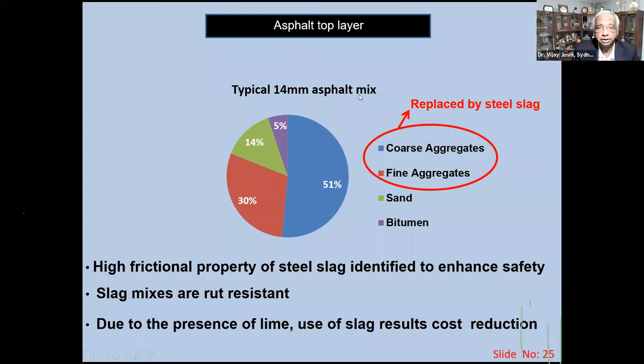Now, this is the typical 14 millimeter mix. When I say 14 millimeter, it is the maximum size of the aggregate in that asphalt mix. If you see that 51% is the coarse aggregate and fine aggregates are 30. So 80% aggregates are totally replaced by steel slag. So another advantage of using this. Now, as I said before, it is high frictional. It is rut resistant because it's heavy. And thirdly, because slag contains lime, CaO, the current specifications say that you have to add lime there to get the bonding between aggregates and bitumen. You don't need that. That CaO is already there. So you have added advantage when you use steel slag in the asphalt mix.